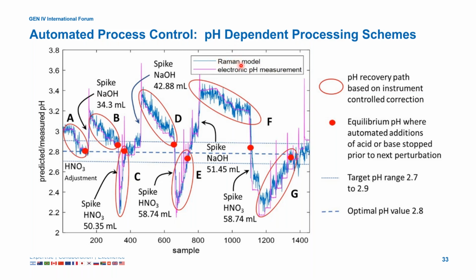I want to point out the Raman model is in the light blue lines that are shown here. That's the real-time monitoring for the Raman model with the PLC control. The pink line is the electrochemical pH measurement from our auxiliary measurement, and those follow exactly on top of, just spot on, our Raman model. So our confirmation is that we're tracking pH properly, and we're also controlling the pH in an automated fashion.